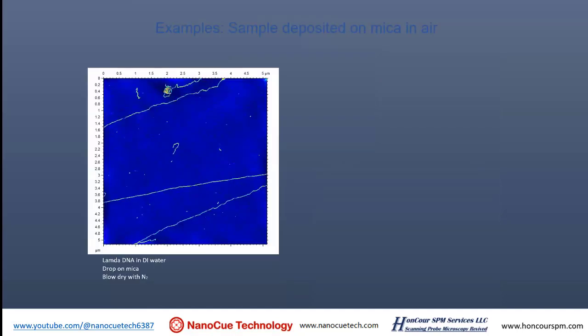Okay, so here's another example of sample deposited on mica surface. This is a DNA sample, lambda DNA, so it's DNA pieces. This sample is prepared so that the DNA is dissolved in water, you drop this water DNA onto the surface, and you blow it with dry nitrogen. When you blow it, it dries the water very fast, and you also stretch the DNA out. So DNA is stretched out and separate from each other very nicely. If you just drop the DNA on the surface of mica, you will create a sample that is a lot of aggregates, and sometimes you don't even see DNA.